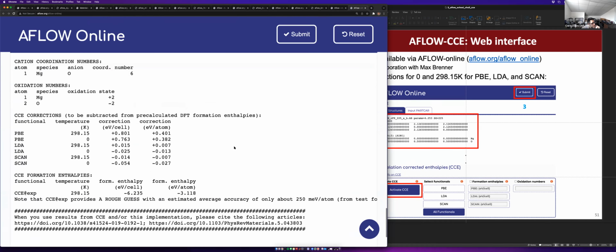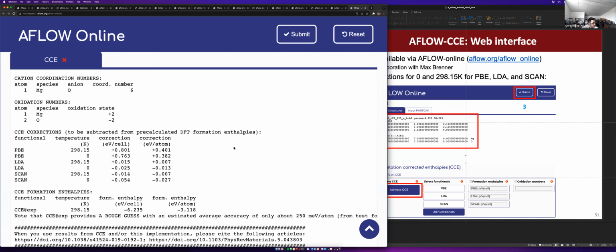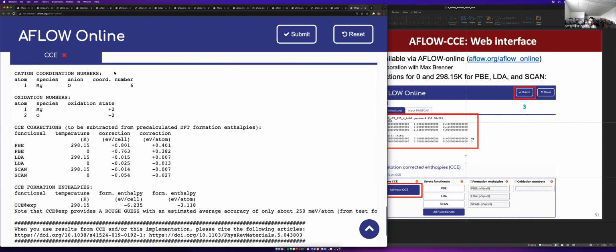So first, it tells us what CCE detects to be the coordination that we're trying to correct. So you see here that we basically have our system where we have magnesium in the middle, and we're going to have 6 oxygen atoms around it. Okay, so if this does not match with what you expect structurally, well, then you're going to expect that the results are not going to be consistent. But in this case, this is exactly what we expect here. So it's just telling us what analysis was done based on the coordination it was able to calculate. Based on this coordination number, we can get back our oxidation numbers.